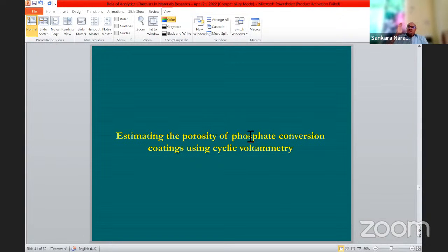So if you apply a phosphate conversion coating on the steel, and then you apply a paint film, even if there is damage during transportation or something like that, there will be corrosion on the damaged zone, but it will be localized only to the damaged zone. It will not spread. So the idea of phosphate conversion coating is that it prevents the spreading of underfilm corrosion.